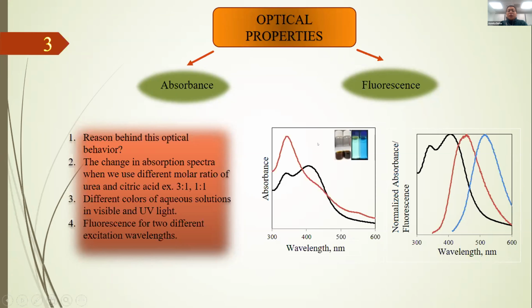Although we got two different peaks in the absorption spectrum, in the 3:1 molar ratio sample, the 405 nanometer peak becomes much stronger and more prominent. But in the other one, it is hardly visible. We also recorded the emission spectrum with 2 different excitation wavelengths and normalized it with the absorption spectrum, as you can see in this graph.